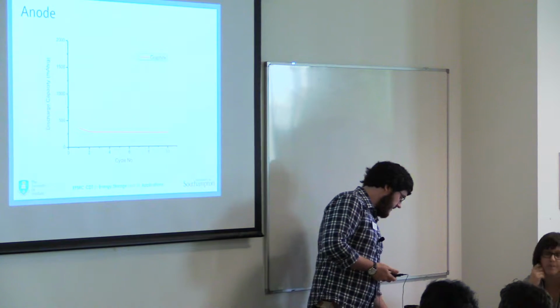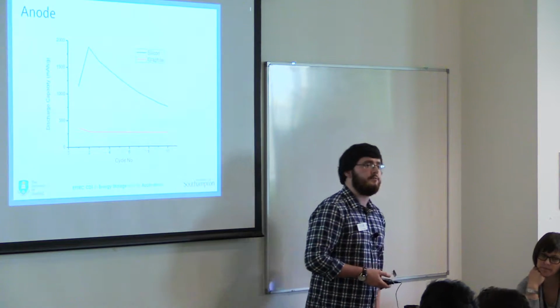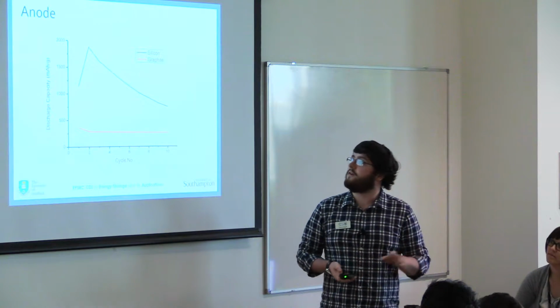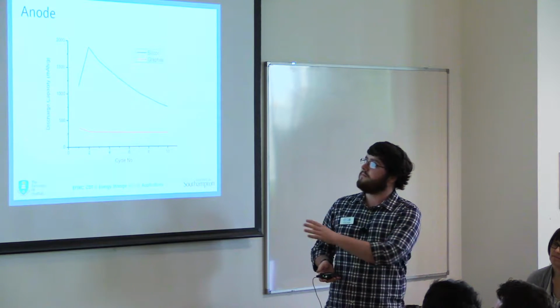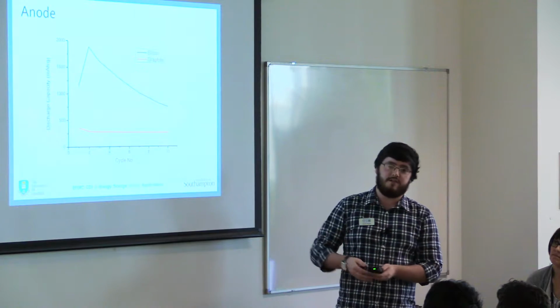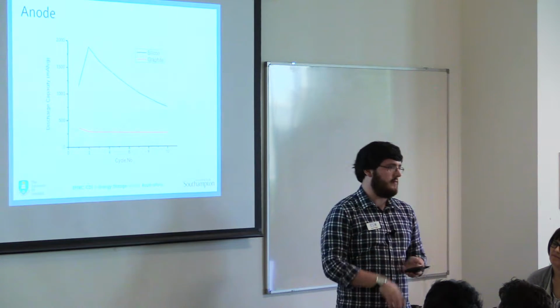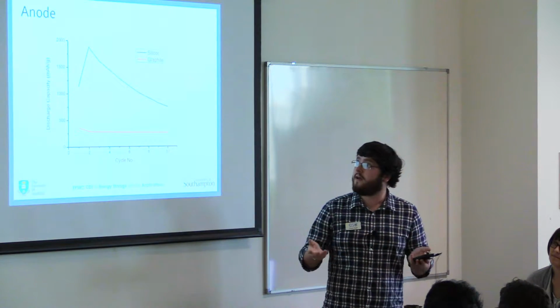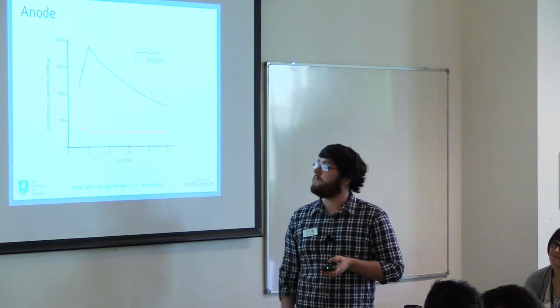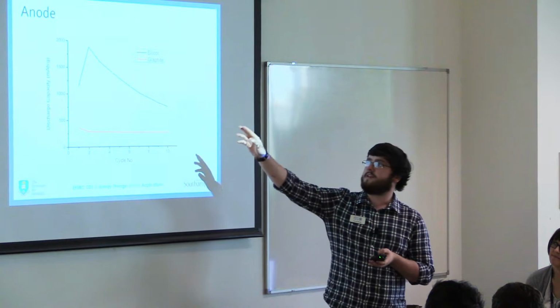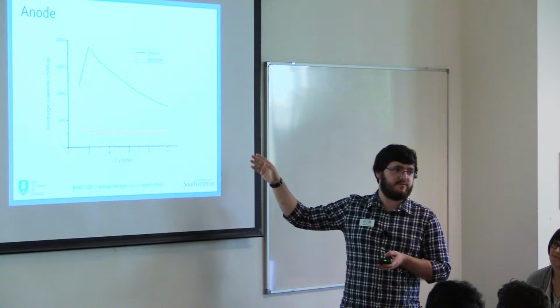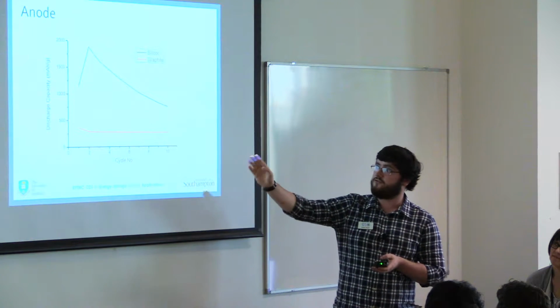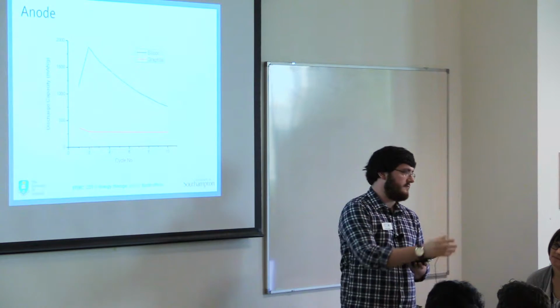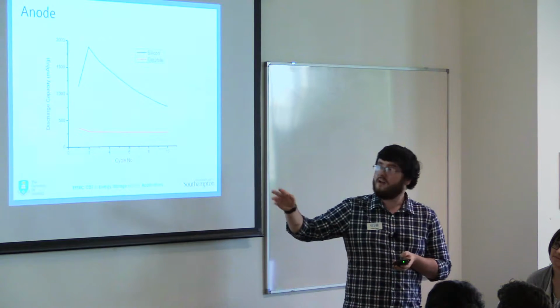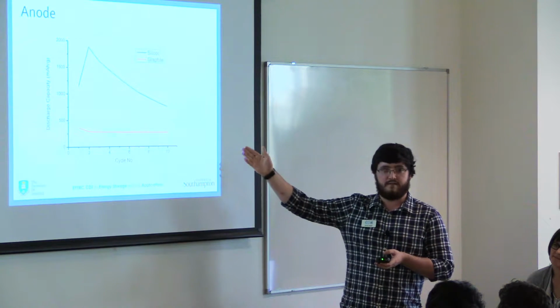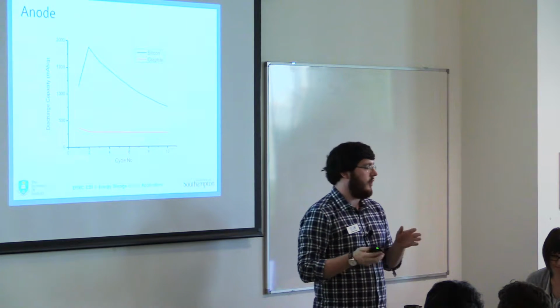I am going to deviate away from carbon-based anodes, though, and look at silicon-based anodes. What I hope is immediately clear is that we can achieve significantly higher capacities, over an order of magnitude higher, up to 2,000 milliamp hours per gram. But we experience extreme cyclability issues. There's a very drastic capacity fade, and that's just across 10 cycles. If I were to extend this graph to 30 cycles, the capacity would be similar to graphite. So that is what I wish to address.